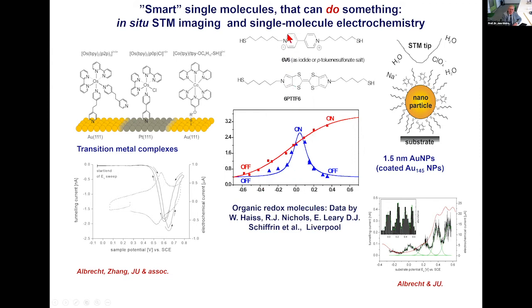The tetrathiafulvalene, so-called, has a very sharp maximum, like the one we would like to see. But the floppy viologen molecule shows a different behavior. It is a kind of sigmoidal correlation, and this will have to be interpreted differently. It is either a simple Nernstian equilibrium between the oxidized and reduced form, or it is gated electron transfer. You will get this kind of behavior if the molecule has to twist somehow before the electron transfer occurs.